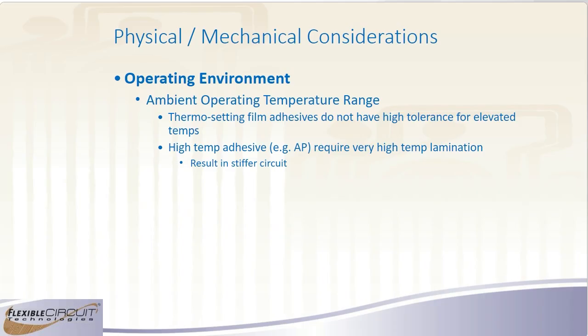If you look at operating temperature, flex circuits are, for the most part, all made with thermosetting adhesives bonding everything together. It's a film adhesive that comes in a B stage as a raw material. And when the manufacturers laminate them together, they cure and stay flexible when they're cured. The problem with thermosetting adhesives is they do get fragile when they're heated up, and it doesn't take a whole lot of heat for them to start getting fragile. A flex can handle a 550-degree solder float for 10 seconds pretty easily, and that's usually just a static exposure to the heat. And for the most part, they can run at well over 100 C continuously without any problems if it's static.